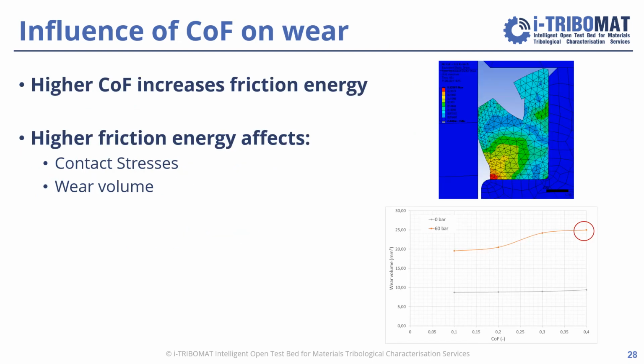So finally, let's look at the influence of this coefficient of friction on wear. If the coefficient of friction is higher, then this increases the friction energy in the contact area, and this directly affects the contact stresses, which also increase. And if contact stresses are higher, then the wear volume is higher, according to Archard's wear law as introduced before.